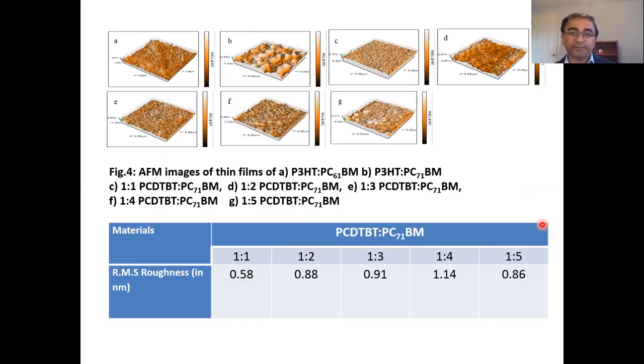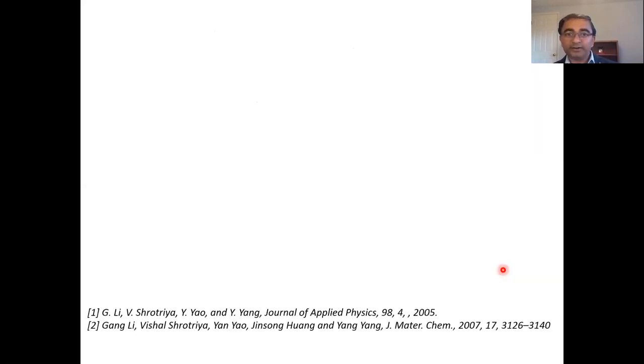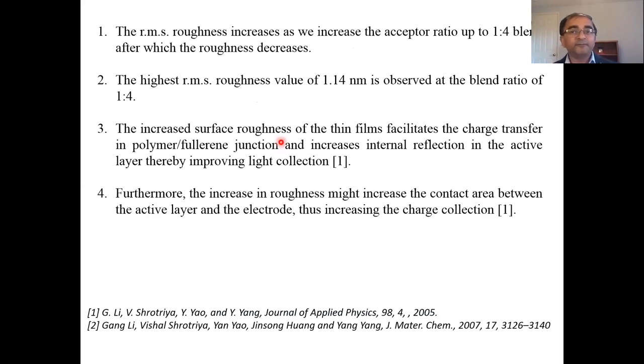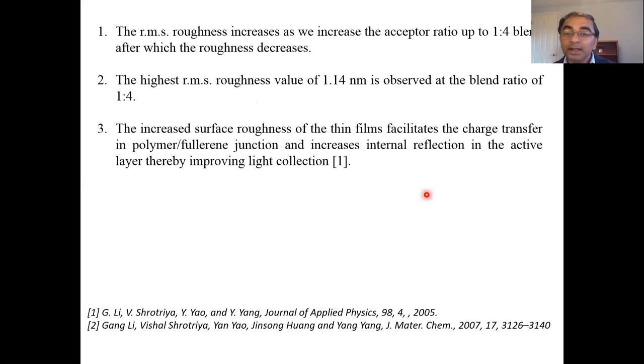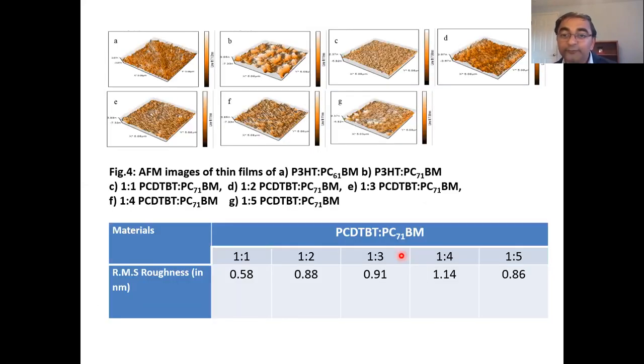This is AFM. You can see from here that this is a very interesting thing. Up to 1:4, the roughness increases, and after that the roughness decreases. Now, what is the effect of this roughness? The increased roughness of the thin film facilitates the charge transport in the polymer fullerene junction and increases internal reflection in the active layer, thereby improving light collection efficiency. Also, increasing roughness might increase the contact area between the active layers and the electrodes, and hence it also increases the efficiency of the device. So there are positive aspects of increasing the roughness, and the optimized roughness is at the 1:4 blend ratio.